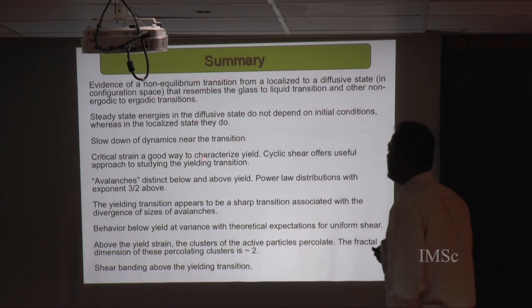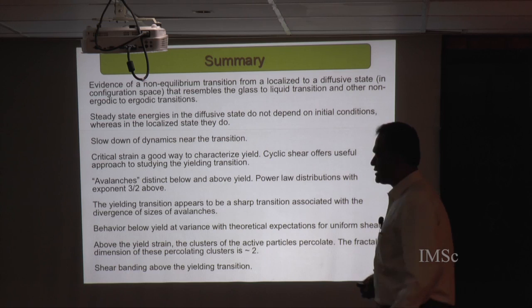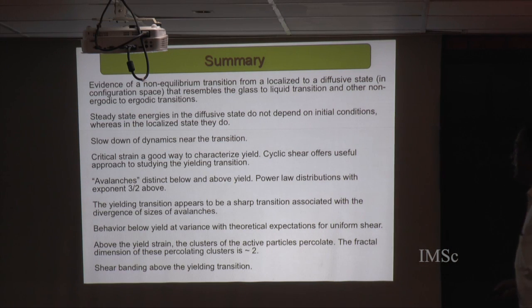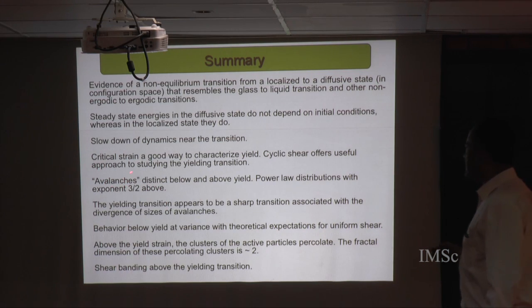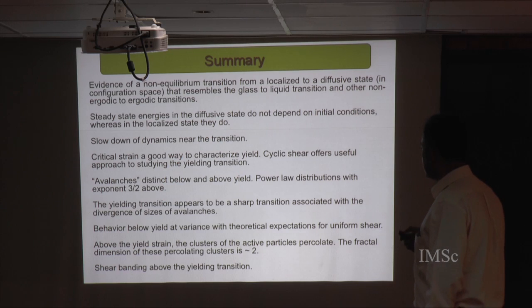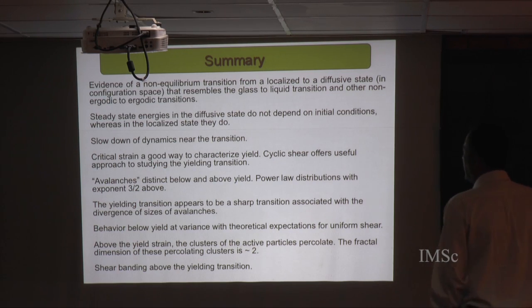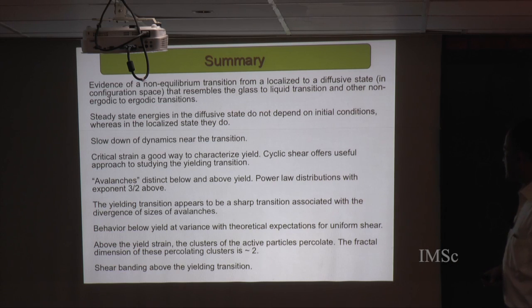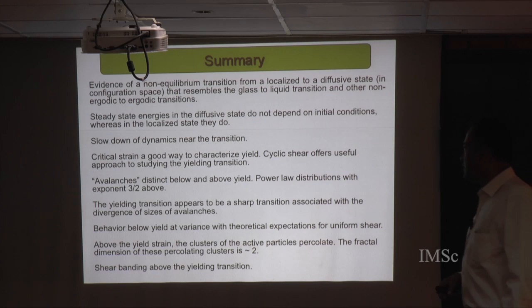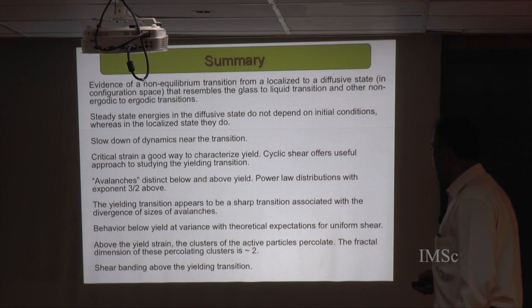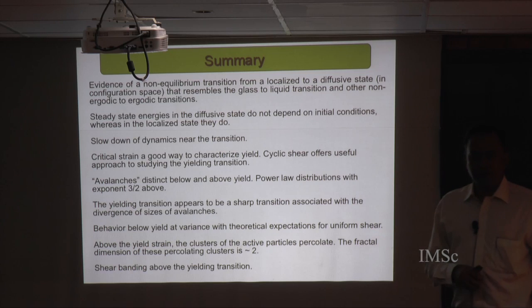This transition is a good way of characterizing yielding, and we have avalanches that are distinct below and above the yield point, with power law distributions with exponents of 3/2 above. The yielding transition appears to be a sharp transition associated with the divergence of the sizes of avalanches, with behavior below yield at variance with theoretical expectations of uniform shear.